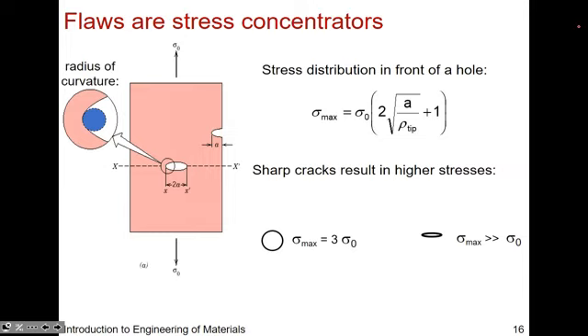So even though as an engineer you know the applied load, the stress that's right at that tip can be immensely higher than what you apply. The way you take a look at that is if you move this over here and take a look at this ratio, you could see, okay, what is the K? What is that ratio right at the tip? How much is the stress concentrated? It could be 15 times as high, it could be 20 times as high. So even though, let's say you apply 100 megapascal, it could be 10x that, 15x, 20x that, right at that crack. And when that happens, it can actually propagate the crack growth and fracture right at that point, even though your applied load, sigma naught, is well below your tensile strength.